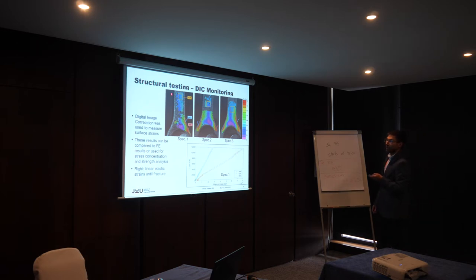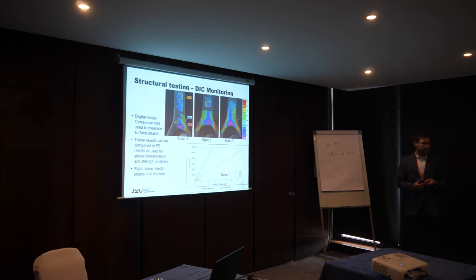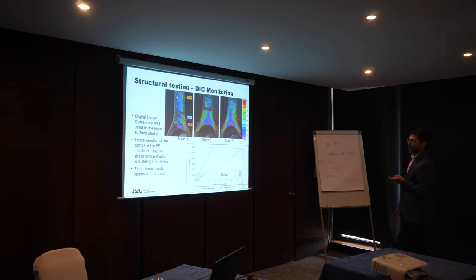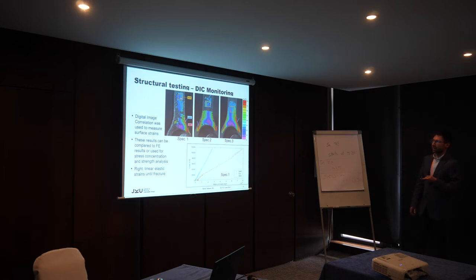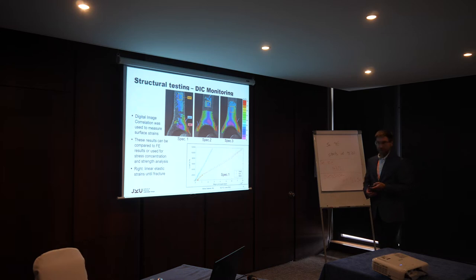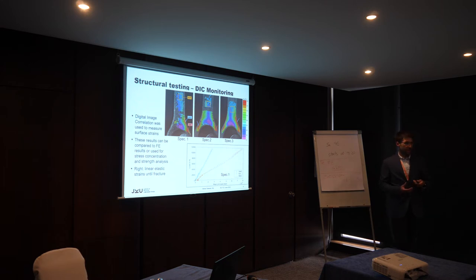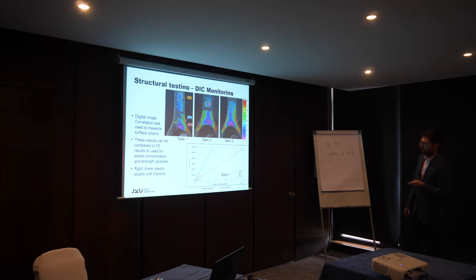You can see this vector pattern — we use a 3D digital image correlation system to measure the surface strains. The first validation is in the shaft region, where we assume near uni-axial tension. We evaluated a surface rectangle and checked stiffness in the shaft, which corresponds well with classical laminate theory for fiber stiffnesses and fiber volume fraction. Specimen one with higher fiber volume fraction gives higher stiffness, specimens two and three show slightly lower stiffness.